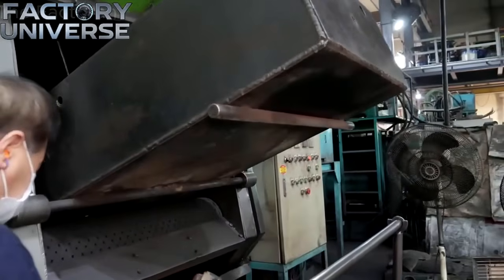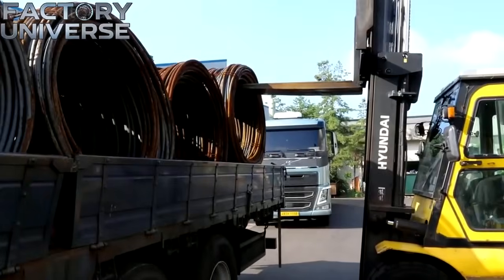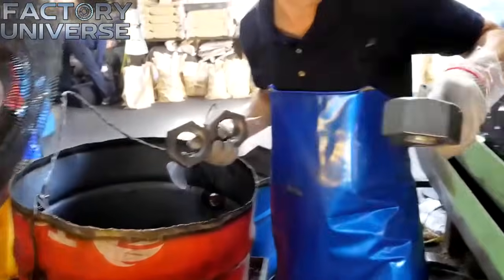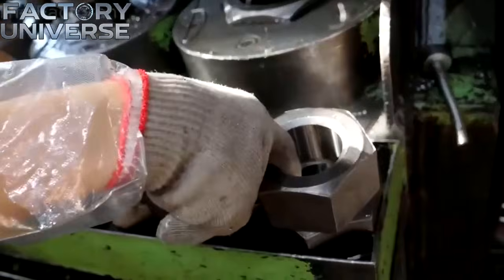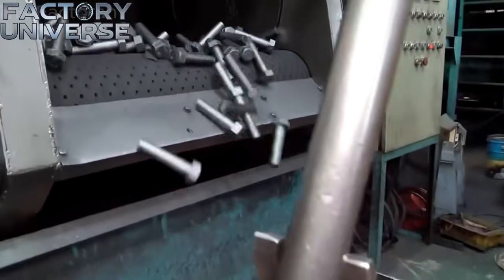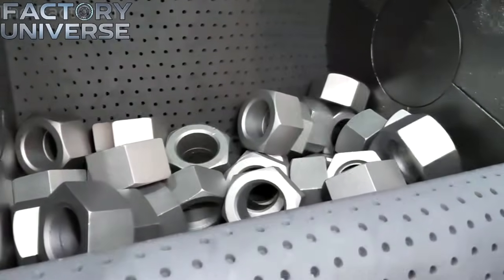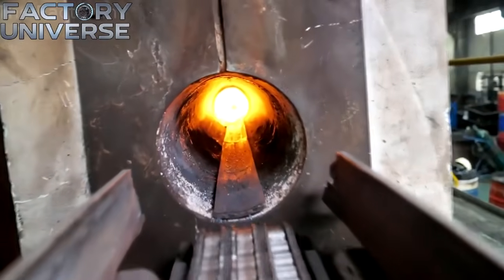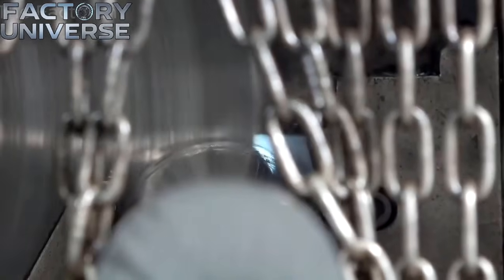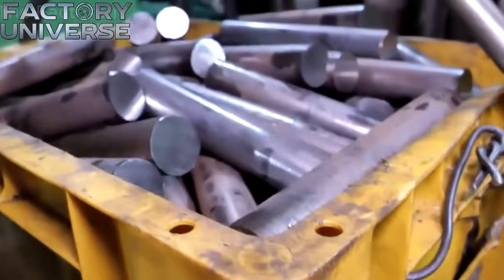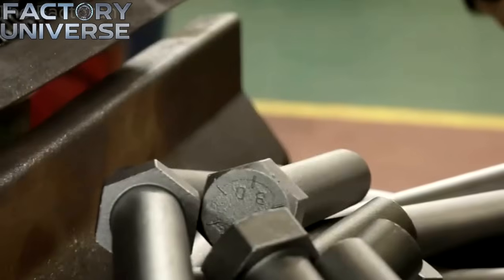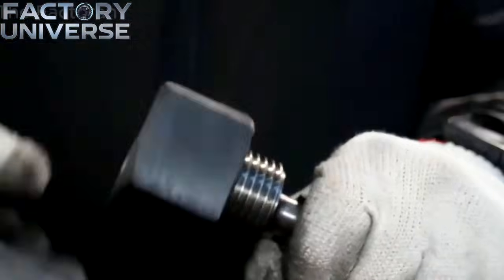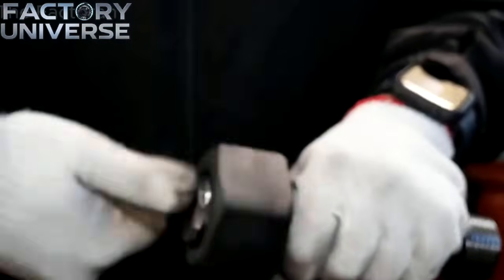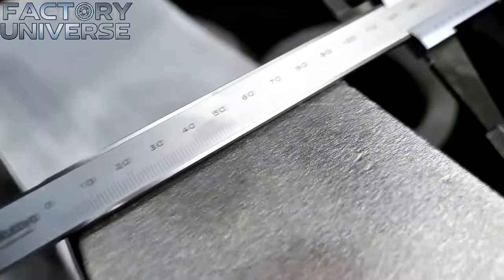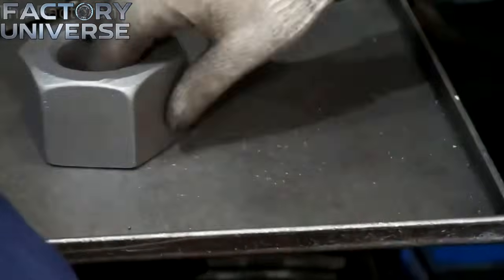This is not the limit. The temperature is monitored with extreme rigor to prevent surface oxidation while keeping the core soft enough for the high-pressure molding process. Bolts undergo a specialized thermal treatment that targets only a specific section of the material. Instead of heating the entire bar, an induction system focuses energy solely on the head portion of the billet. Within a span of a few seconds, the front end of the steel begins to glow a bright orange red, signaling it has reached the ideal forging temperature. Meanwhile, the shank located behind the heated zone remains significantly cooler and maintains its original rigidity.